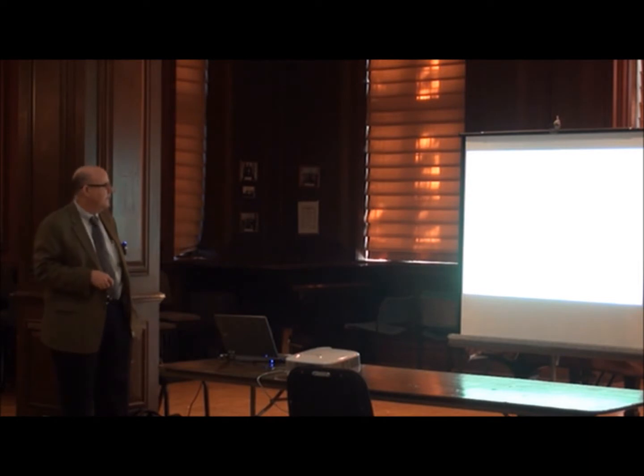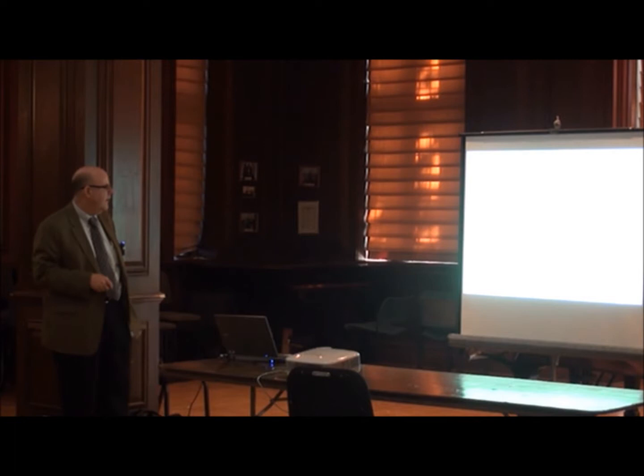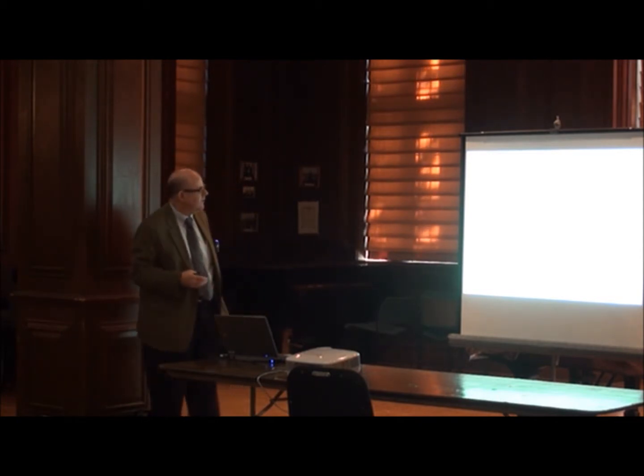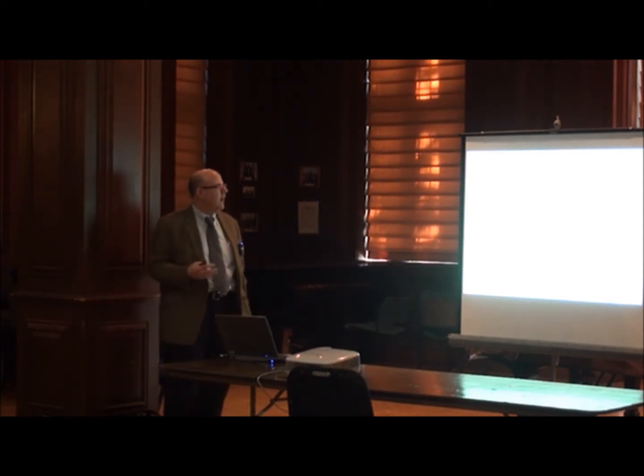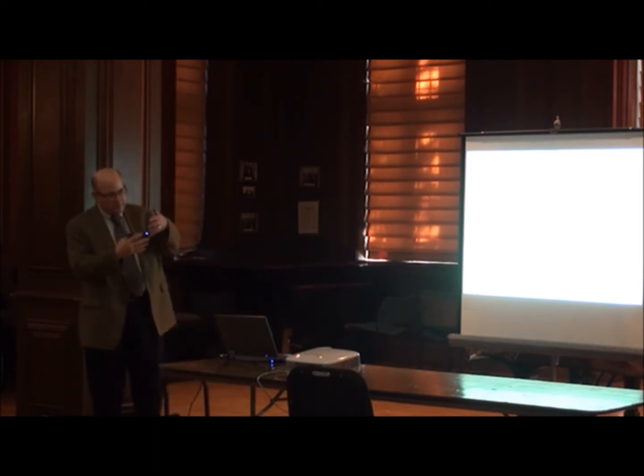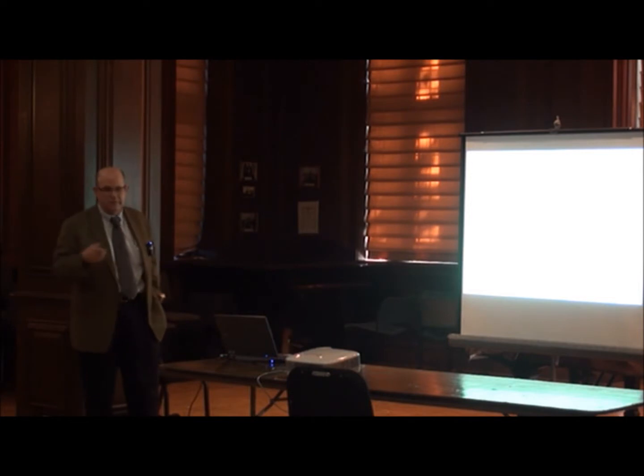So this is kind of an interesting result that Greenwood and Williamson came up with, and it works because it basically says the frictional force is proportional to the load. I increase the force, I increase the frictional force because the frictional force is just the real area of contact times the shear strength, and that it has no dependence on apparent area. So this was like another big breakthrough in the whole story. In words, we're just basically saying that friction is the shear strength of the real regions of contact. Whatever those regions of contact are, we get some kind of adhesion or whatever going on at that interface. So if I know the real area of contact and I know what the shear strength is at each of those little junctions, I have an estimate of friction.